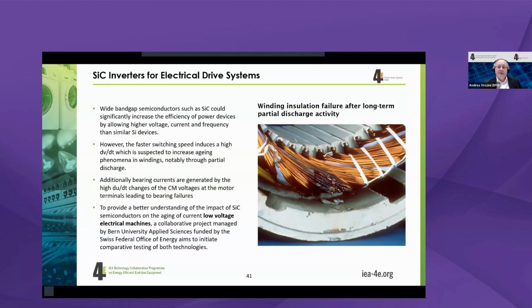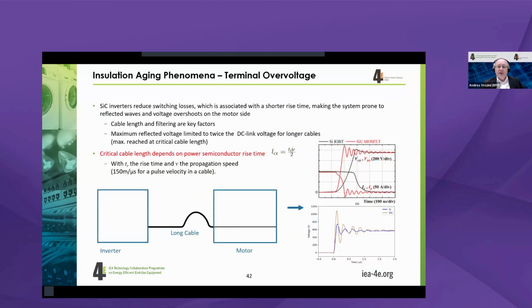And if you look at the two main failure modes which can happen, we see that the higher switching speeds could lead to winding insulation failures because you would have additional higher over voltage. The second point is the additional bearing currents can lead to damages on the bearings. We had similar discussions about roughly 40 years ago with the introduction of IGBT semiconductors.